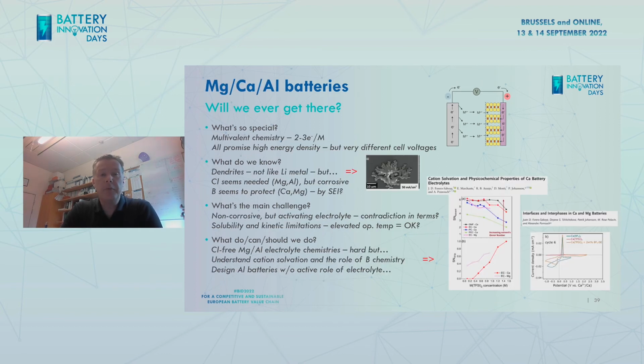So this might sound very pessimistic, and this is actually where I myself prefer to work. So I don't know what that says about me. But all these chemistries where we're thinking now about multivalent batteries, we have metal anodes, which all promise high energy density. That's the common denominator, but they also have very different cell voltages, where magnesium is 1 volt above lithium approximately, calcium is very close to lithium, and aluminium is 1.5 volts above lithium. So that's quite different things.